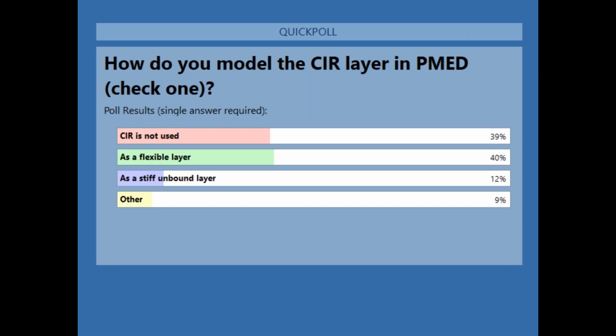Sure. All right, so looking at the CIR again, very similar with the pavement structure. So we got a new HMA surface mix. I did a recycled CIR layer, the remaining asphalt. Then there's that 6.5-inch aggregate base. And then certainly when you model it as an asphalt layer, you got to put in that aggregate layer down below. And rather than going through all the rigmarole of everything, we did do a couple of different comparisons between a 4 or 6-inch SMA layer or an HMA SM layer. We varied the thickness of the CIR layer, and so that's why that remaining layer of asphalt goes from 7 to 5 inches, depending on what we adjusted for the CIR layer. So there's where that difference is.